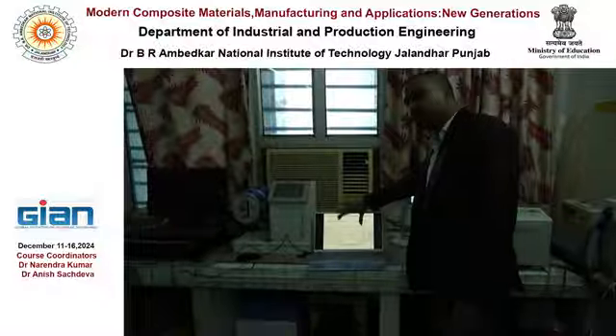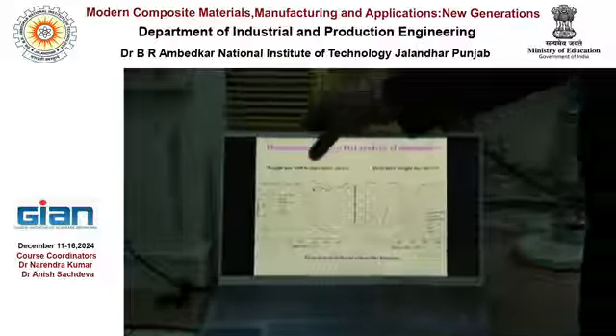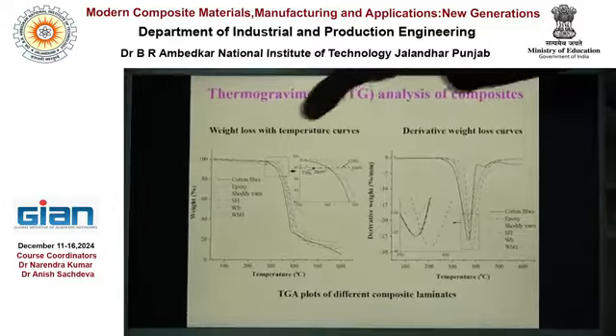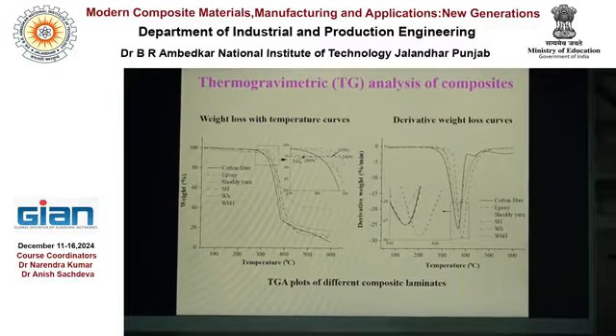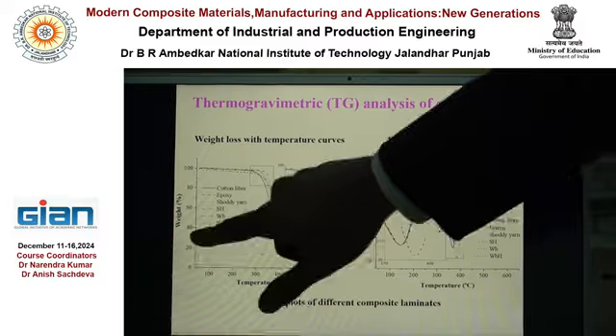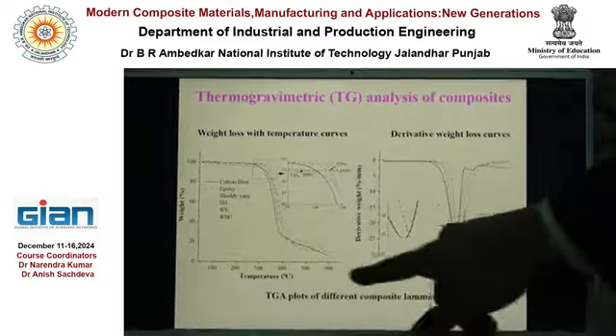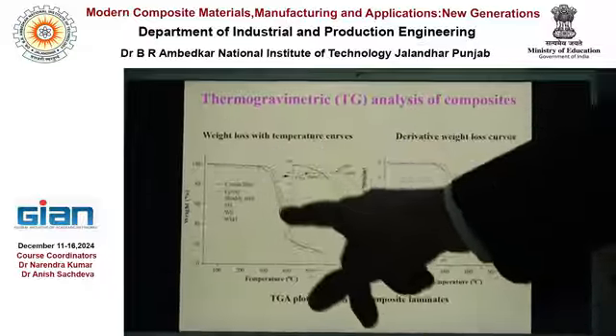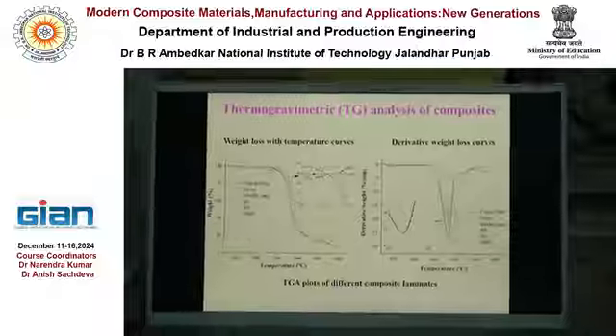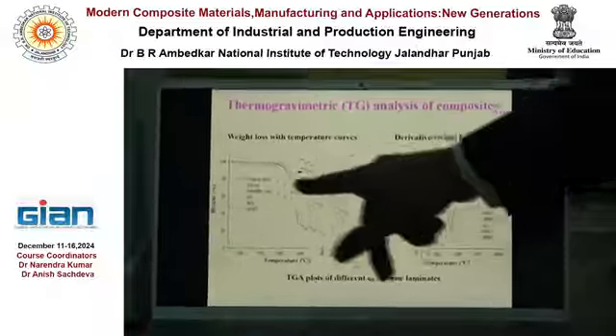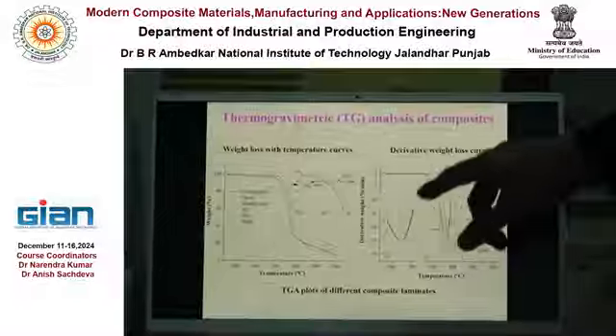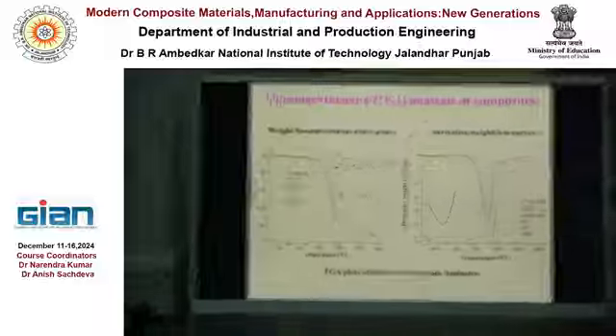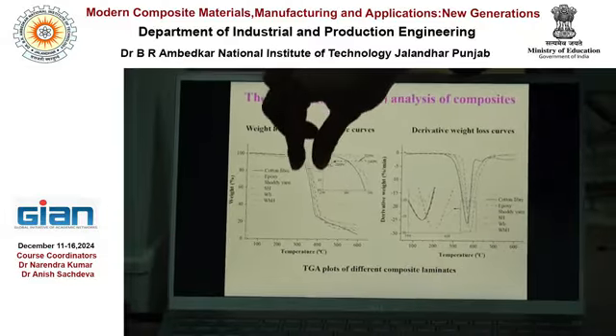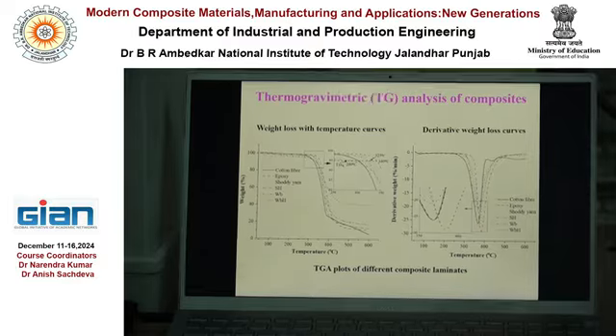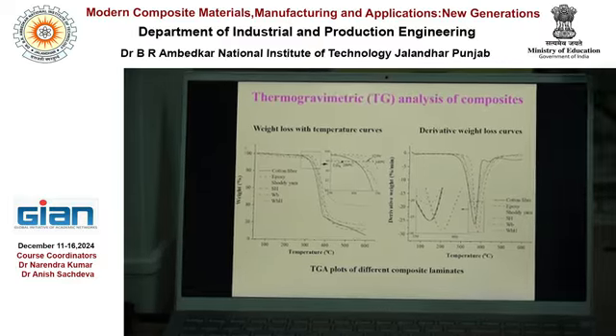Thermogravimetric analysis. These are the typical plots you see in the TGA analysis. One is the weight loss with temperature curve, and another is the derivative weight loss. These two plots you get. On the y-axis you have weight, on the x-axis you have temperature. With increase in the temperature, you see how much is the reduction in the weight of the composite. 100 means the initial weight of the composite material, and with the increase in the temperature, you see how your composite is degrading, and at what temperature it shows a very high change. For example, this region of 300 to 400, where we can see the maximum reduction in the weight of the composite material.